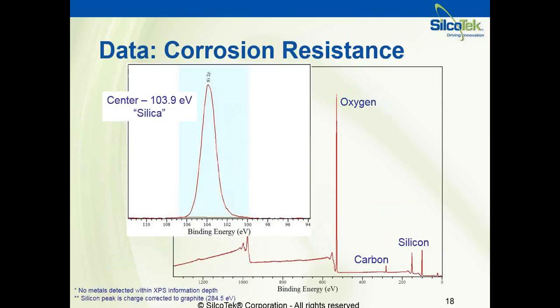And here we are working to adapt the data to leaching simulations using SIMS or XPS, but again, we wanted to show here that you see the coating residing over the binding energy for silica, and again, that there's no presence of other metal ions. You're simply getting the silicon oxide ceramic-like coating with the Dursan.